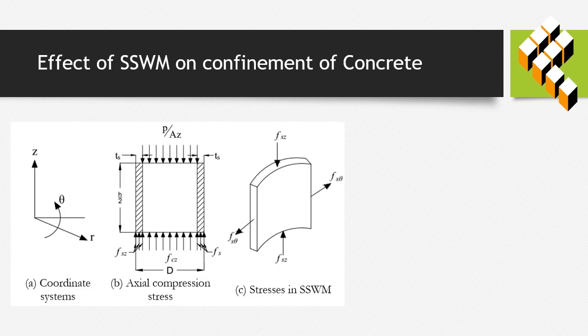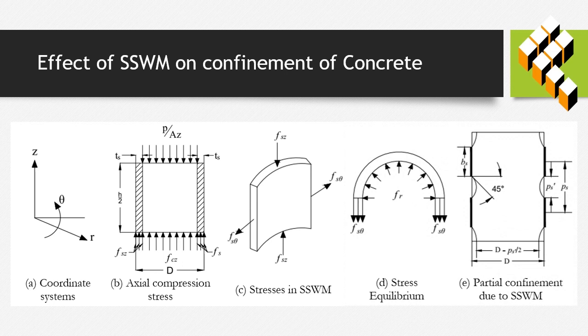Analytical studies to estimate the compressive strength of FRP confined concrete are available in the literature. However, there is a lack of analytical models to quantify the role of SSWM in confinement of the concrete cylinder. The SSWM wrapping exerts a passive confinement action on the concrete cylinder due to the lateral expansion of the concrete under the axial load. Uniform radial pressure created against the lateral expansion of the SSWM confined concrete develops the tensile hoop stress, which leads to an increase in axial stress and the corresponding increase in lateral strain.